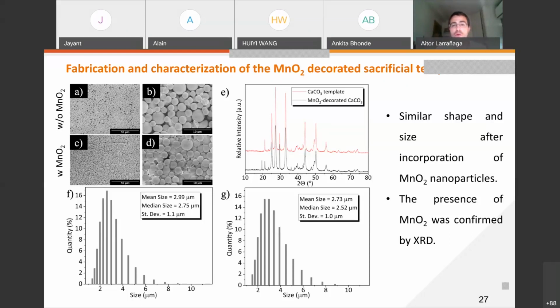So the only way we could prove the presence of manganese dioxide nanoparticles on our calcium carbonate template was by XRD. Here, as you can see, the diffractogram of the calcium carbonate template after being incubated with manganese dioxide presents two new peaks at 18 and 38 degrees, which are characteristic of manganese dioxide, and finally confirm the presence of manganese dioxide nanoparticles in our calcium carbonate template.